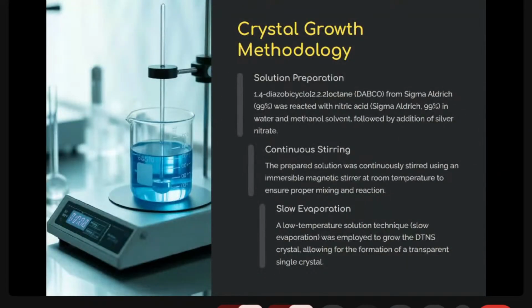Now, crystal growth methodology. I have used the slow evaporation solution technique. So, 1,4-diazabicyclo[2.2.2]octane, DABCO, is mixed in the solvents water and methanol, followed by the addition of silver nitrate and the nitric acid. Then it is stirred continuously using a magnetic stirrer at room temperature, and then we filtered the solution and kept it undisturbed for a longer period of time to take the supersaturation and nucleation and get good quality single crystals.